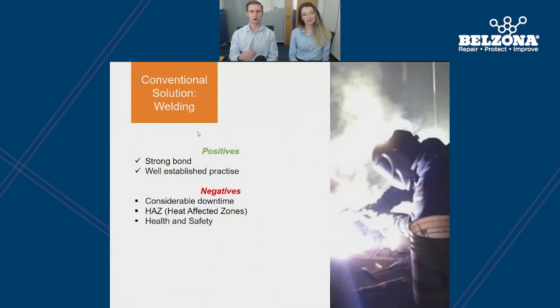So when we talk about adding strength back into the structure of a substrate, welding a plate onto a defect area is a very common method of repair. It provides a strong bond and is a very well-established method. However, before a tank can be welded, it must be drained, which means lengthy downtime and also a loss of resources. So welding also creates a heat-affected zone, so it introduces heat stresses into the metal, which can result in further problems such as cracking later down the line.